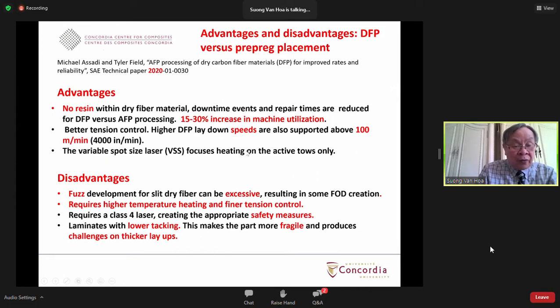However, there are disadvantages. One is the development of fuzz. You have fuzzing of the fibers because they are dry fibers. In this case, it can result in foreign object debris on the laminate. It also requires higher temperature heating and fiber tension control. Because you use higher temperature heating, you have to use a strong laser, and then you have to provide safety measures because it can be dangerous in case it hits somebody. Also the laminate has lower tack, which makes the part more fragile and produces challenges on thicker layers.